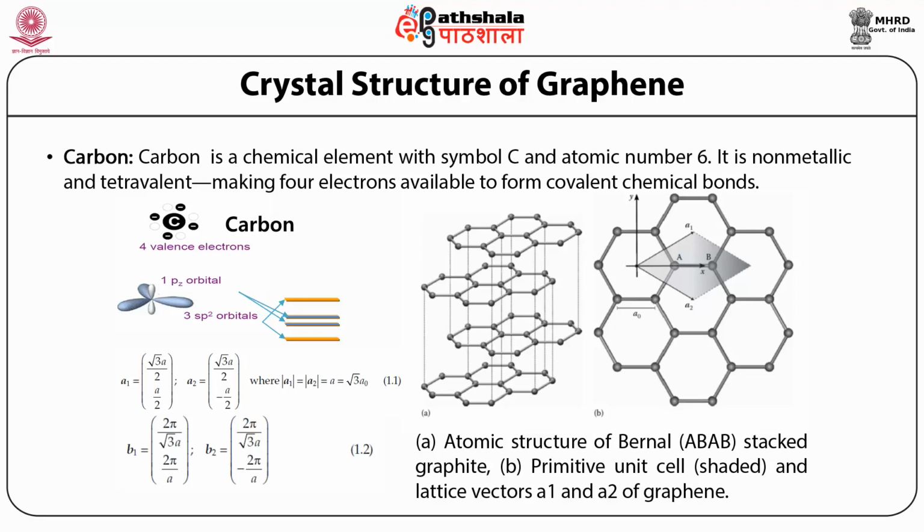For graphene, a primitive unit cell can be defined as the smallest building block from which we can construct the graphene lattice. The primitive unit cell of graphene consists of 2 atoms due to its hexagonal structure, which we can label as A and B in figure B. Lattice vectors can be defined as the vectors joining equivalent points in adjacent unit cells for monolayer graphene.